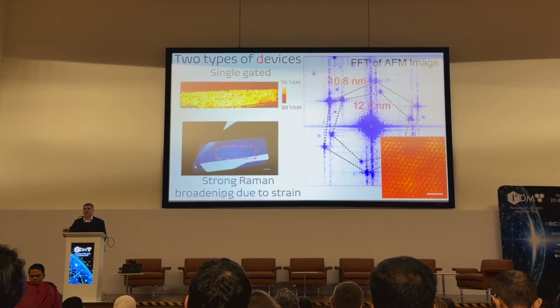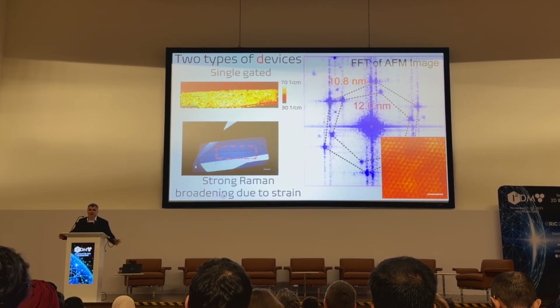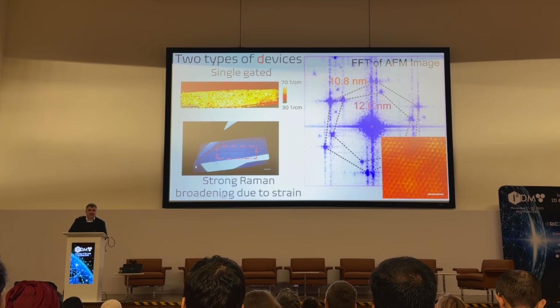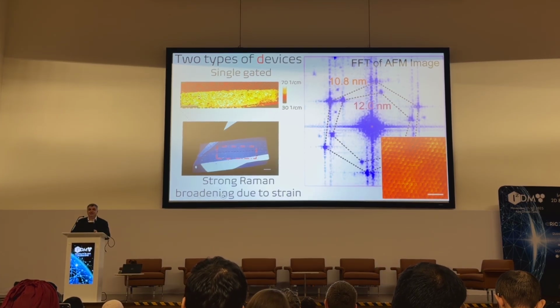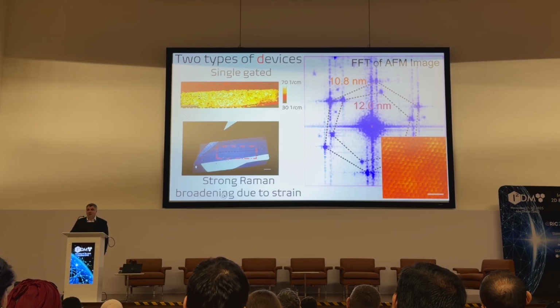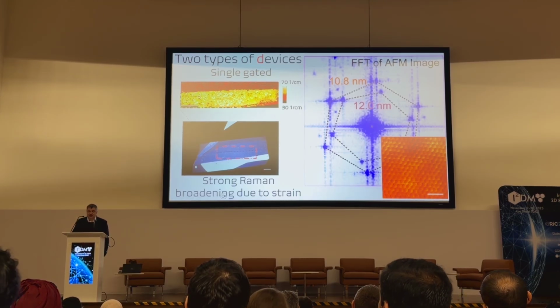And you can also see it from Raman as well. If you measure the 2D peak, it would be like 70 inverse centimeters, really broad, and it shows you that your strain is strongly accumulated now in graphene. If it is singly aligned, then it would be about 30 maybe. If it is double, it may be 45. So the presence of monolayer and double alignment really shoots the strain up to 70.